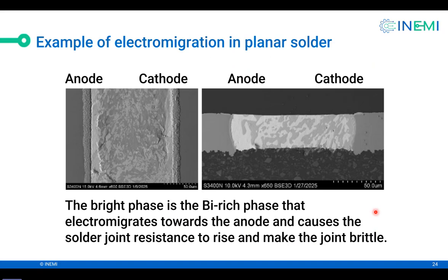Before I begin, this is a typical planar solder joint. We can observe the solder joint after electromigration. You can see that this brighter region is bismuth collected on the left side. On the right side, this region lost the bismuth.